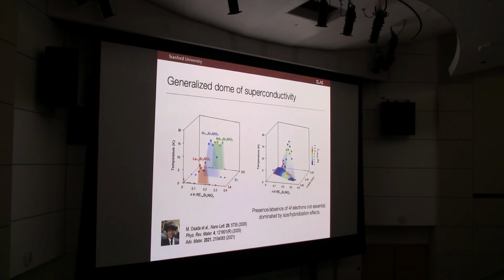It appears to be not the case, and we can collapse kind of all our data. Here it's parameterized in terms of the c-axis lattice parameter. So Bob, to your question, this is unconstrained, but the in-plane is constrained to the substrate. That's common in all of these studies. And so we suspect we're dominated by size and hybridization effects.